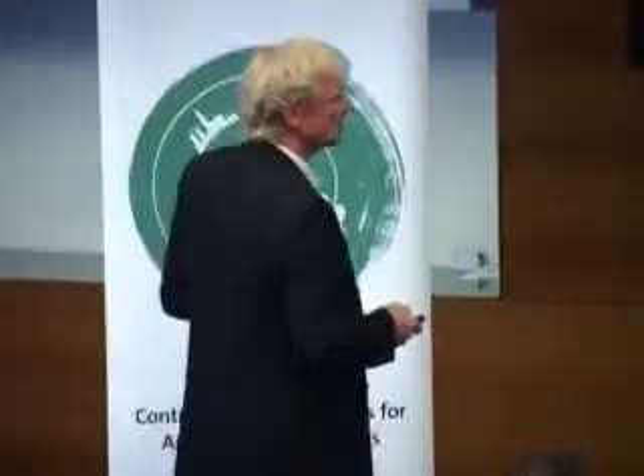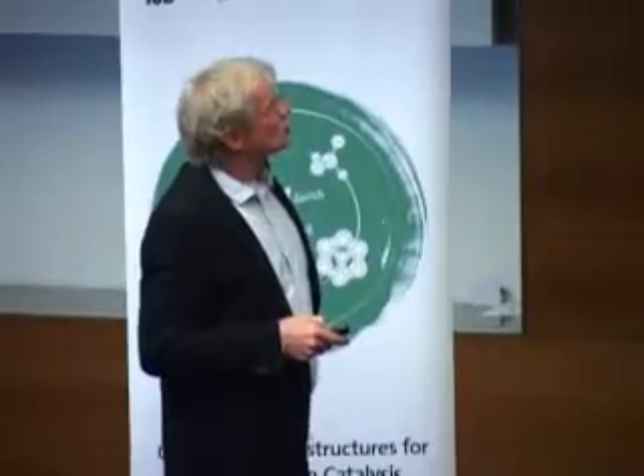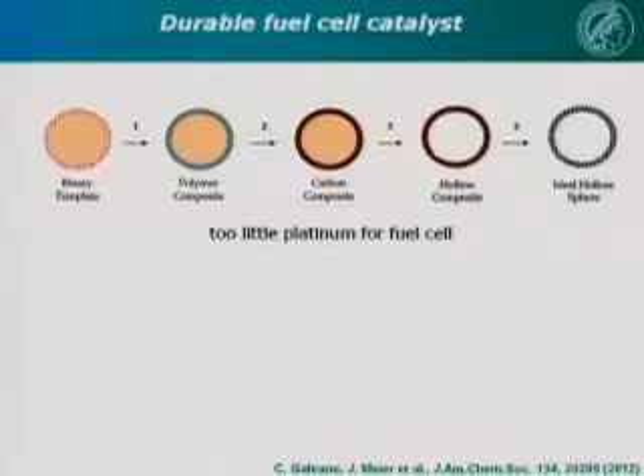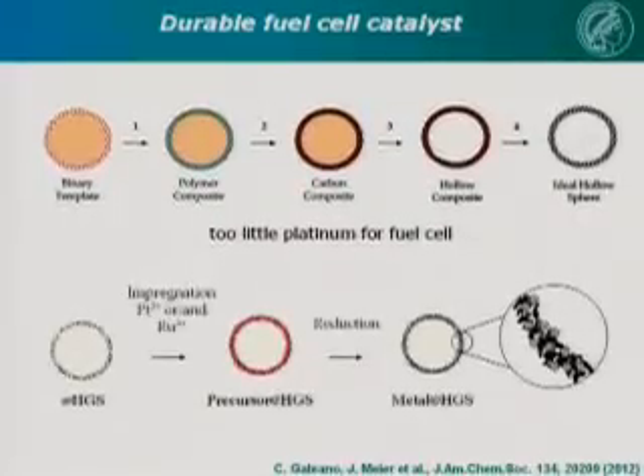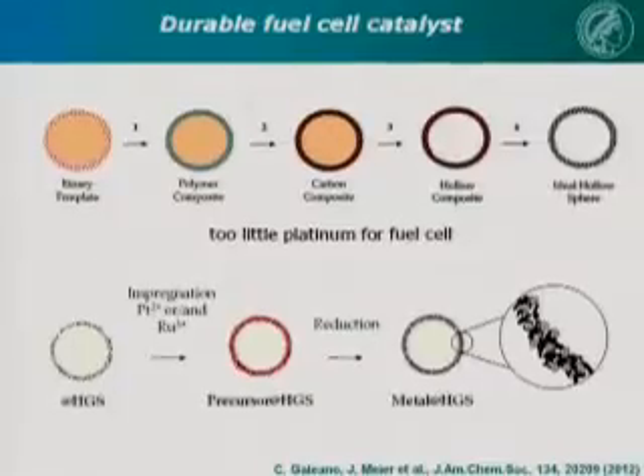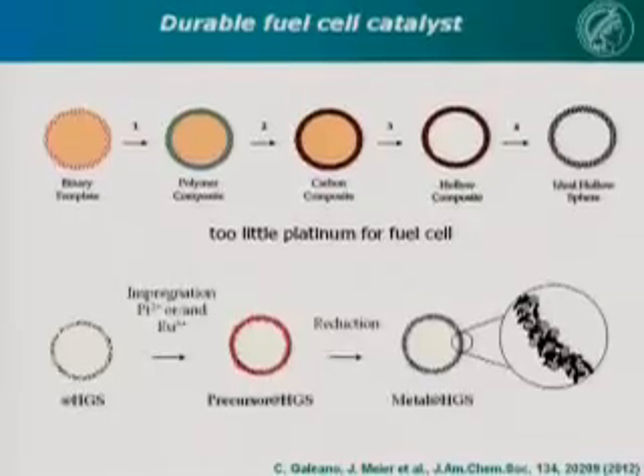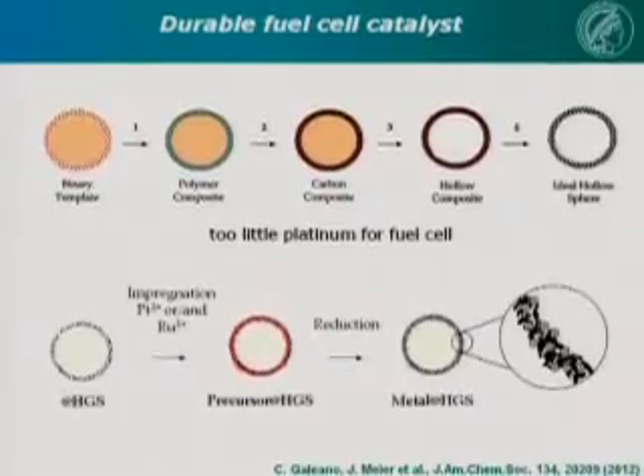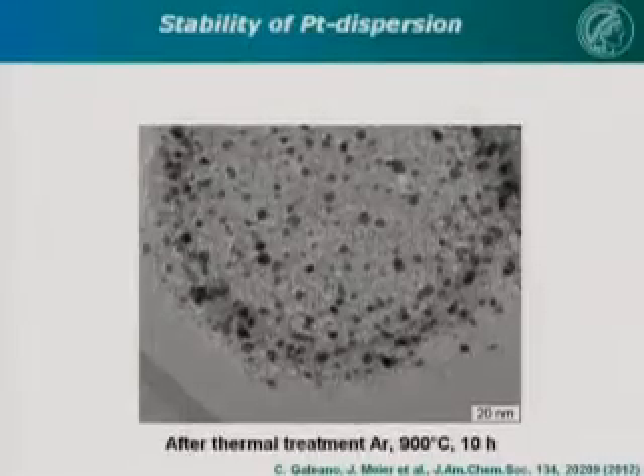Fortunately, Carolina Galliano had a different idea how one could maybe stabilize the carbon particles. She said, well, why don't we just use this process and produce only the hollow carbon sphere, and then not put the gold inside, but use these mesopores in the hollow carbon sphere to protect platinum particles and encapsulate them in the mesopores. So what she did was impregnate platinum into the mesopores, reduce with sodium borohydride, and then do a high temperature thermal treatment to encapsulate it and stabilize it in the pores. And this is what you get.